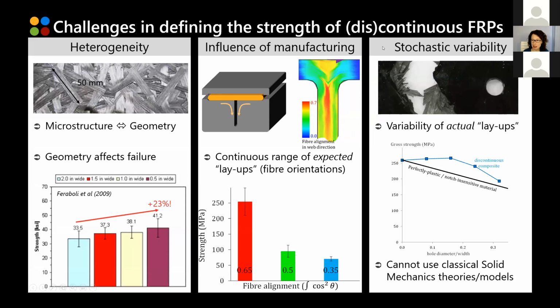A third challenge that we have, and this is something that, again, other people have mentioned before in the scope of continuous fiber composites, is stochastic variability. The plot that you can see here in the center shows the expected fiber alignment from process simulations, but actually you will have a significant amount of variability of the actual fiber alignment of the actual tow layups that you have in a given specimen or in a given structure. And this raises a very odd behavior of these materials. For instance, if you drill a hole in your specimen, it might not fail under tension at the cross section of the hole, but it might fail somewhere else.